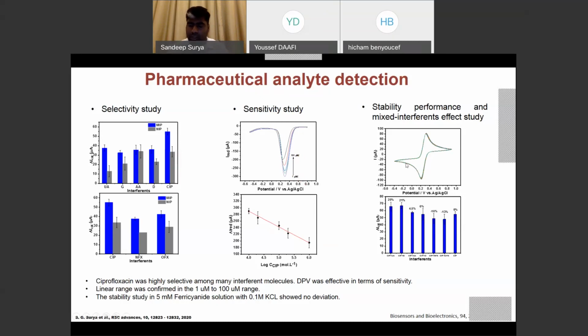Before even introducing any ciprofloxacin into the system for the detection, we swept the bias for around 100 cycles when the MIP is alone present on the working electrode. Thus, we don't see any kind of deviation in its performance in terms of both oxidation currents and reduction currents. Finally, when you introduce the ciprofloxacin into the system, these current peaks tend to come down, identifying the CIP.